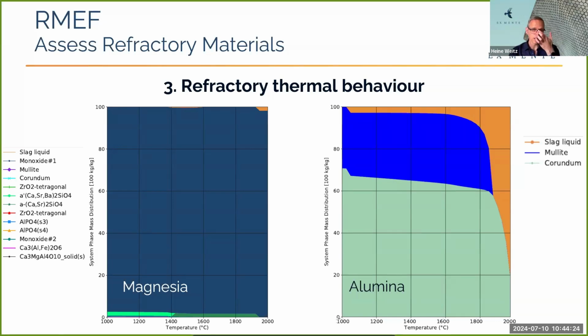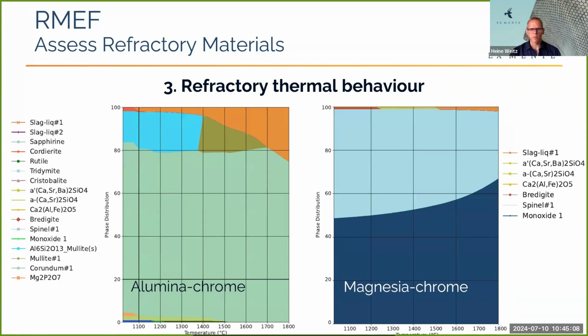On the right-hand side, we've got an alumina refractory. So at 1000 degrees Celsius, it consists of mostly corundum and mullite. But as you start heating it up, you start forming some liquid slag, and that increases quite a lot as you exceed 1800 degrees Celsius. But again, the temperature at your refractory hot face might not be close to your actual slag or alloy temperature. But this gives you at least an indication of how your refractory material will behave as a function of temperature. I'm going to skip over the next one for the sake of time. It's just another example of refractory thermal behavior.